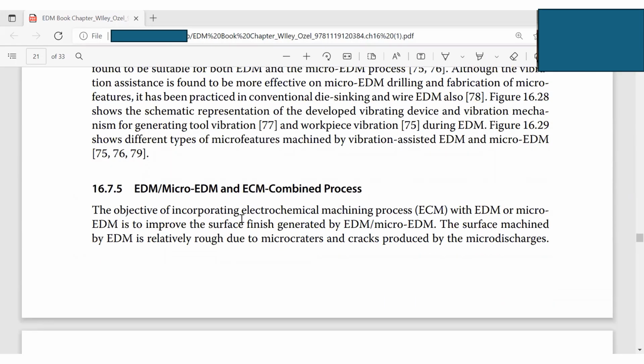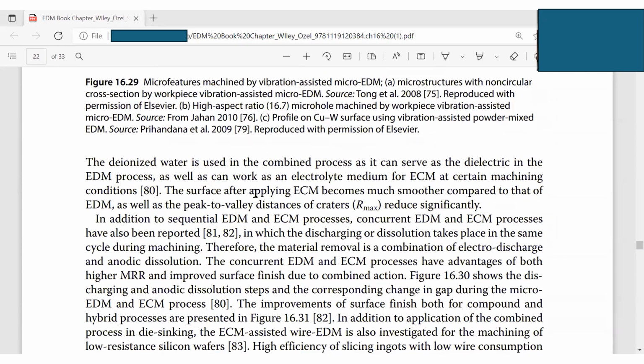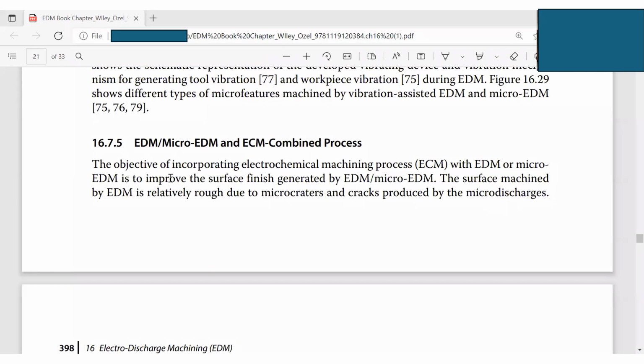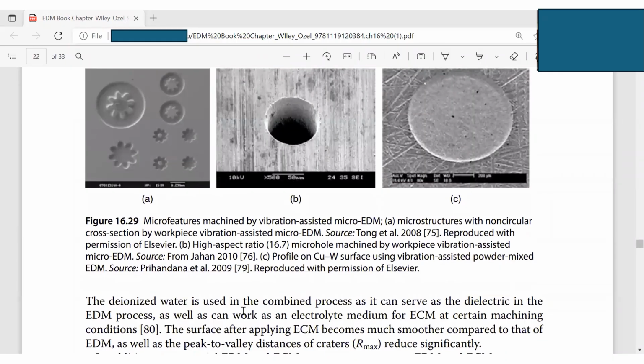And then we move on to the next one, the fifth one: EDM, micro EDM, and ECM. ECM is the electrochemical machining process. So this is very interesting, one the EDM, one the ECM, to improve the surface finish generated by EDM and micro EDM. The surface machined by EDM is relatively rough due to micro craters and cracks produced by the micro discharges. Then you just use deionized water. The deionized water is used in the combined process as it can serve as the dielectric in the EDM process as well as work as the electrolyte, the medium for ECM, at a certain machining condition.